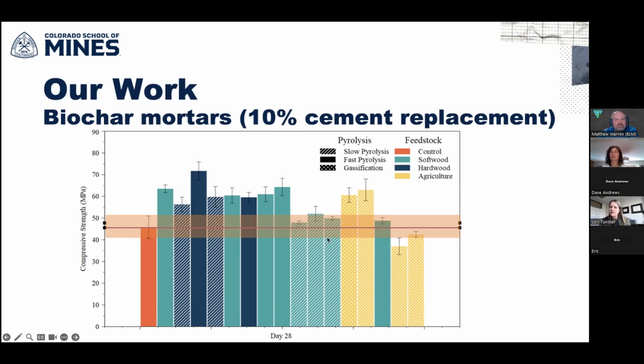So for the strength in cementitious composite, the difference between a mortar and concrete is that mortar contains sand, so fine aggregate, and concrete contains sand and coarse aggregate, so like the rocks. And then cement is just the binding material. The great news is that most of the strength in these systems is controlled by the cement phase. So typically the trends that you see in a mortar would also apply for a cement, would also apply for a concrete. There are some exceptions to that, but that's typically the rule. So this is a cement with the sand, but we would anticipate similar trends for just a cement paste.